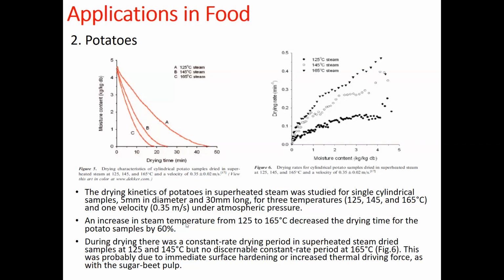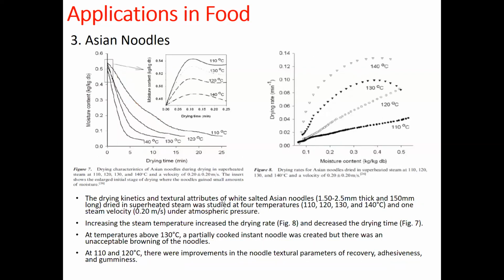An increase in steam temperature from 125 to 165 decreased the drying time by 60%. During drying there was a constant rate drying period at 125 or 145, but no discernible constant rate period at 165. This was probably due to immediate surface hardening or increased thermal driving force, as with the sugar beet pulp.